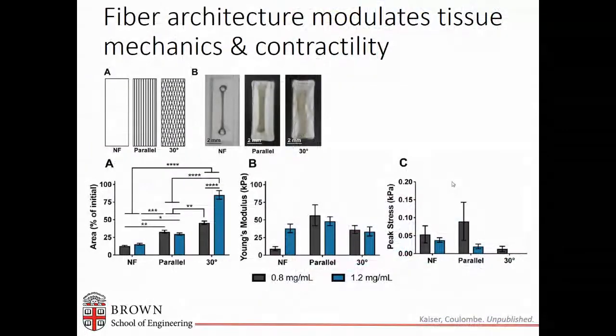So we've continued this work, and we're looking at different architectures, for example, parallel and 30 degree meshes, as well as no fibers, which was our original engineered tissue with just the hydrogels. And we can find that compaction is not as great when you have parallel fibers or even the 30 degree fibers, because these fibers are providing additional stiffness. And so we decreased the concentration of the hydrogel itself to make sure that we got good compaction at this 30 degree angle. And we're continuing this study to look at the stiffness and the mechanics of contractility.